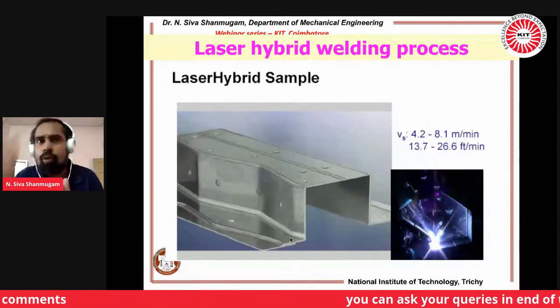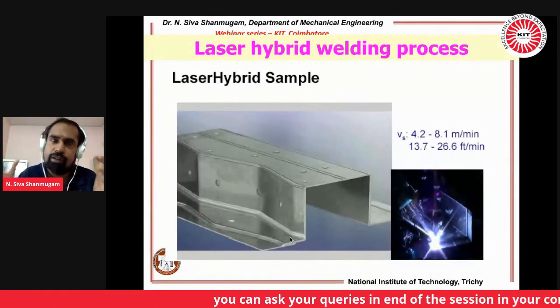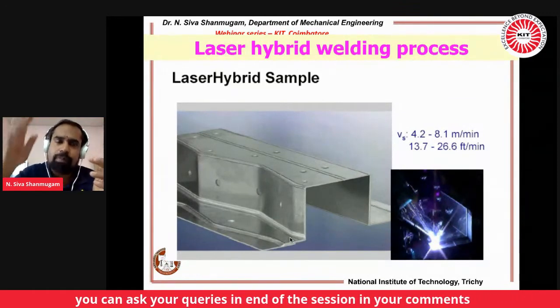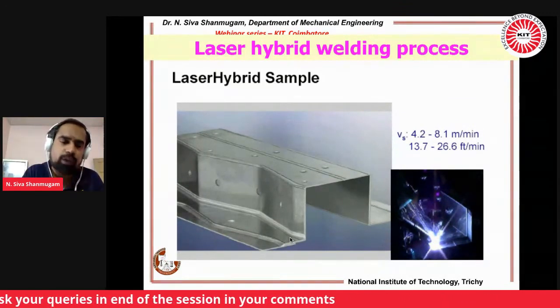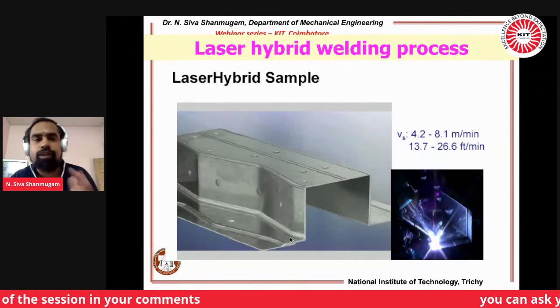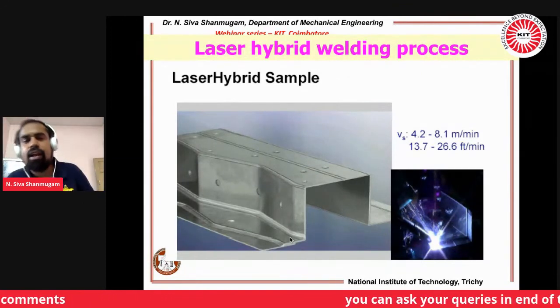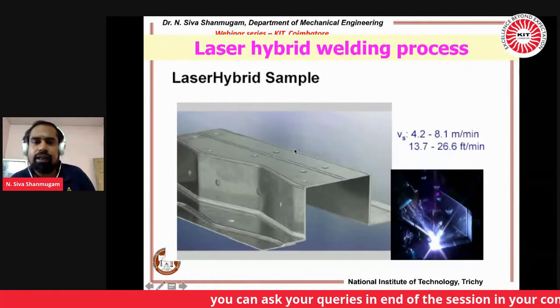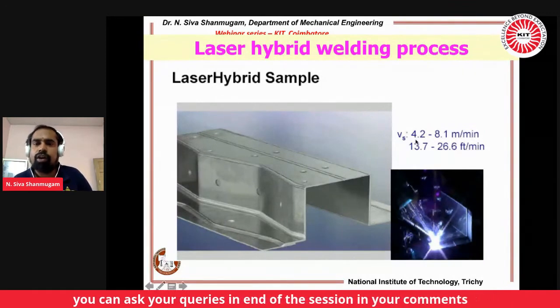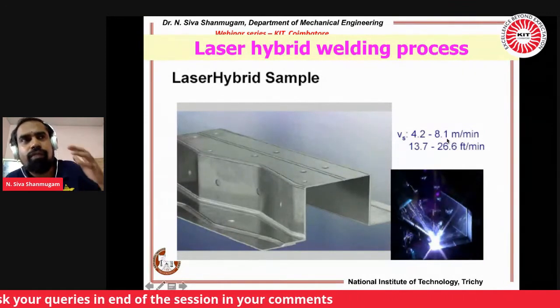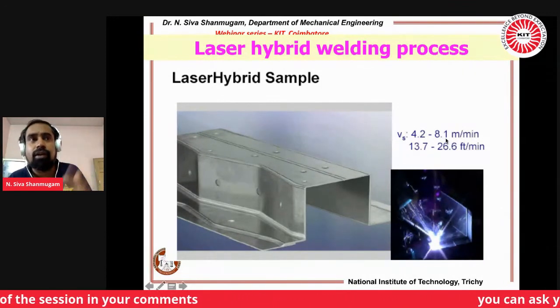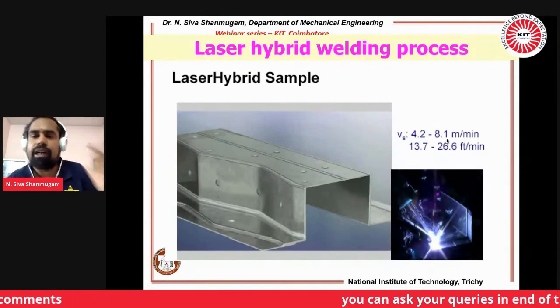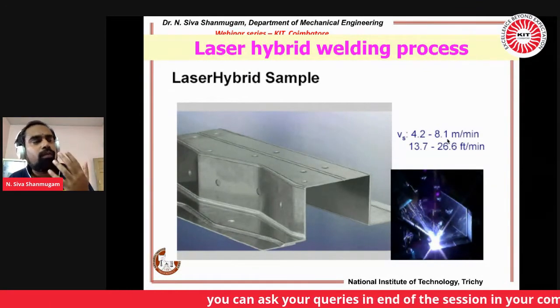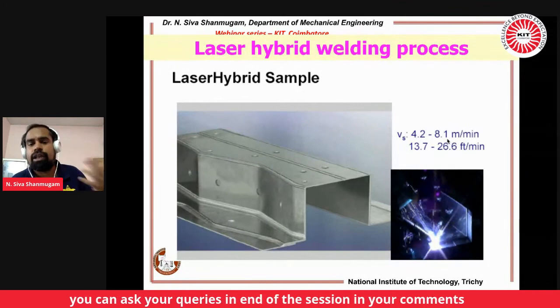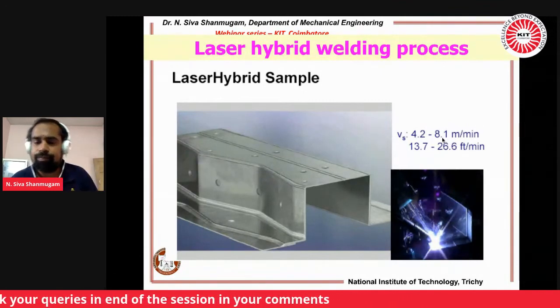Whatever may be the position, you can orient the laser head and do the joint configurations. You can do overhead positions, 2G position or 1G position. Whatever the position, you can tune the laser according to your vision. And this is a welding speed of around 8.1, which is a very high speed, my dear friends. It is around 8,000 mm per minute. In 60 seconds, you can move a very high distance of 8,000 mm.